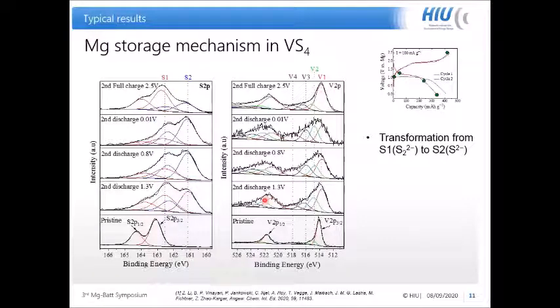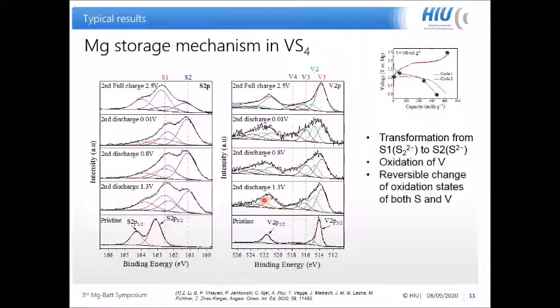In the meanwhile, in the vanadium spectrum, we see a simultaneous change of the vanadium oxidation state to a higher oxidation state. The peak shift is actually towards a higher binding energy.